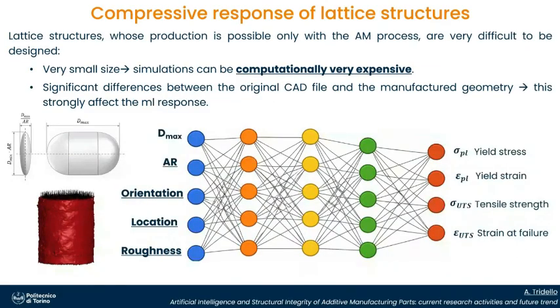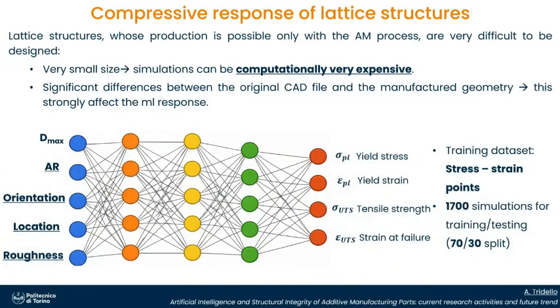For example, we can have as input the defect characteristics: the maximum diameter, the aspect ratio, the orientation, the location, and the surface roughness, and as output the characteristics of the stress-strain curves, so the yield stress, the yield strain, the tensile stress, and the strain at failure, for example. Here are some parameters for the validation, but they are not important.